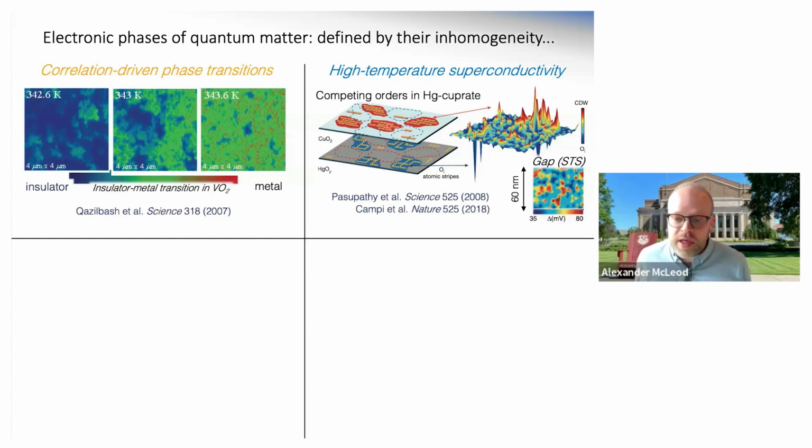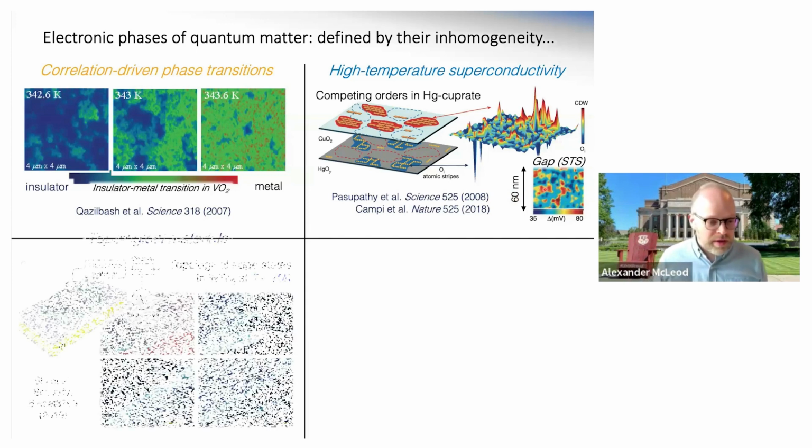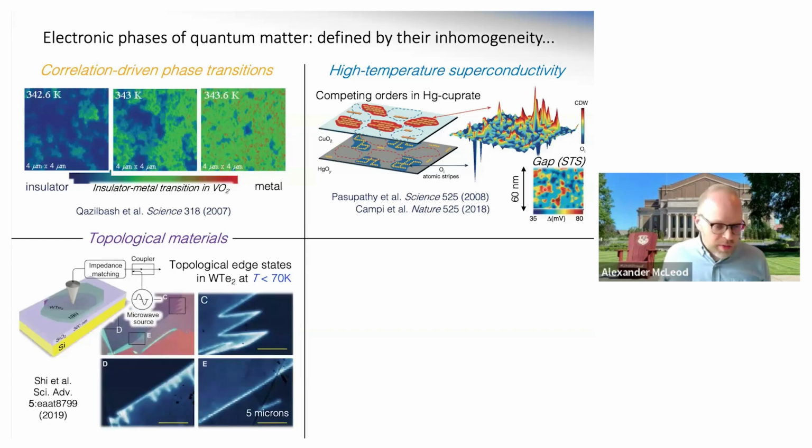And these are some cartoon examples of puddles of superconducting phase competing with other phases of matter. These other phases might be charge-ordered regions of the crystal. And as scanning probes like tunneling microscopy have shown, the intensity of the superconducting state, which is in this color scale right here, varies on length scales as small as 10 nanometers or even smaller, because this phase is competing with other phases down at these really small length scales.